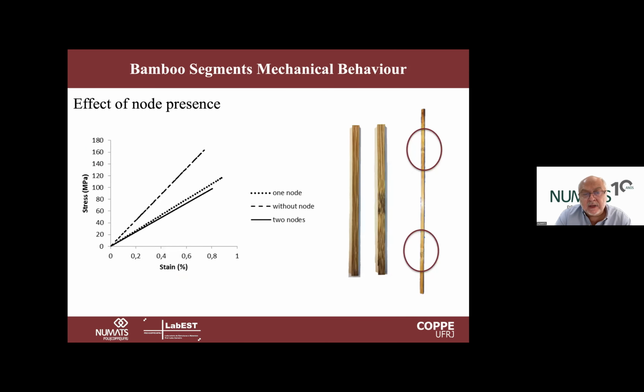So the influence of the number of nodes: the nodes work like natural defects because we have misalignment of fibers in this region. So when we put it under direct tension, the influence of one or two nodes, we did the test also in longer strips because this is how we are going to use it. Normally it is going to have many nodes along the strip when we think about a structural use.